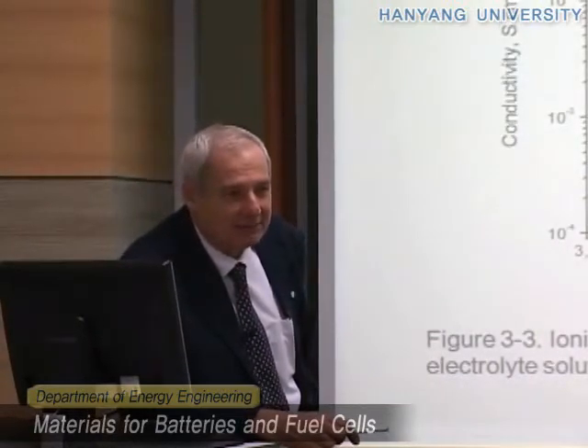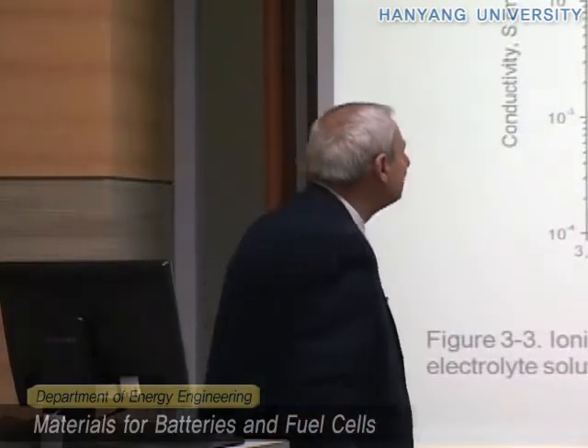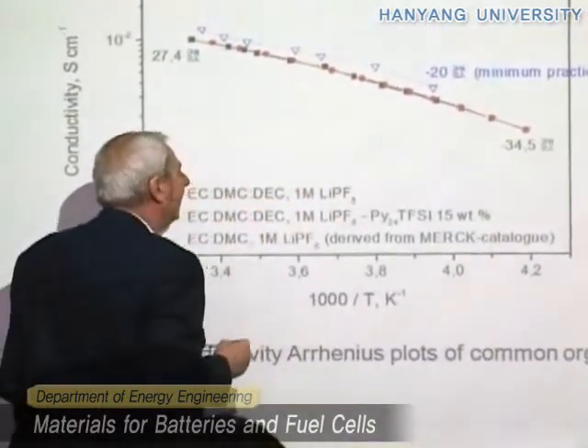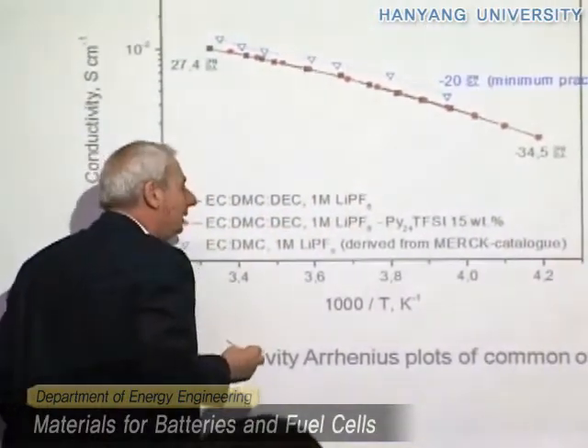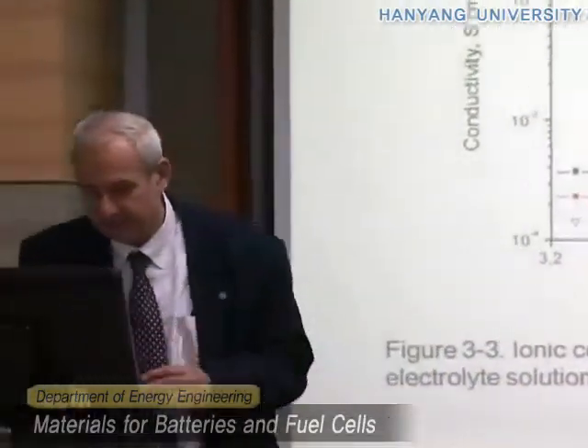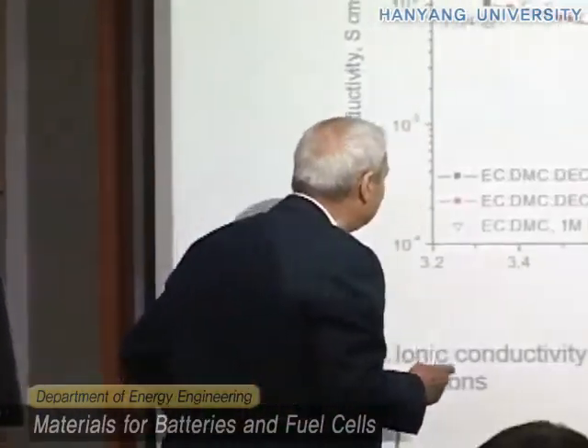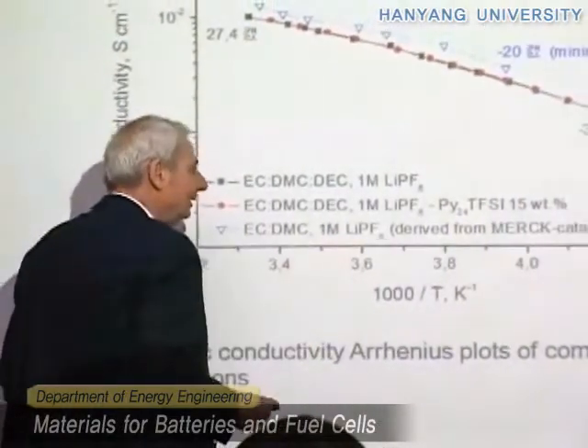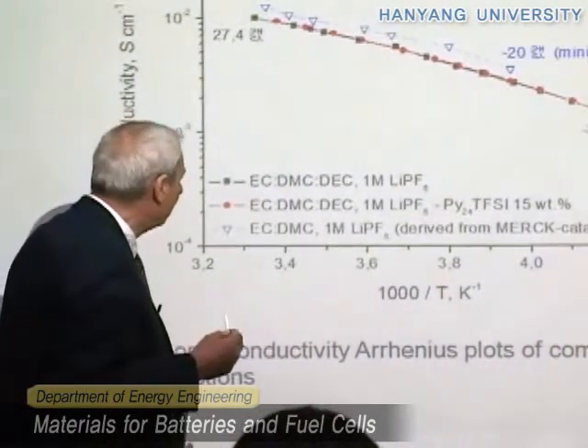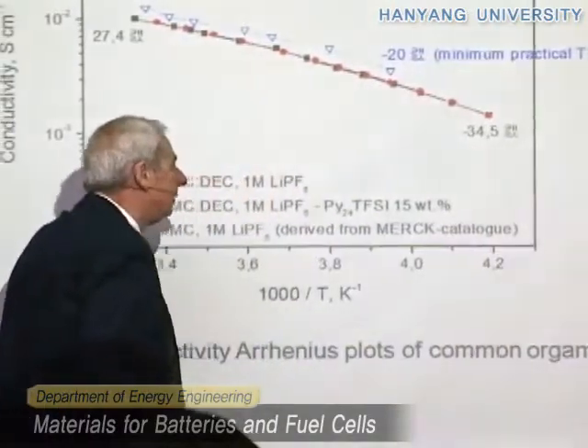Maybe you need a battery operating at low temperature. If you take the standard electrolyte, you cannot go beyond minus 20. But if you add a material that has very low viscosity, as seen in the previous table, you can actually go down to minus 34 with still a good conductivity.